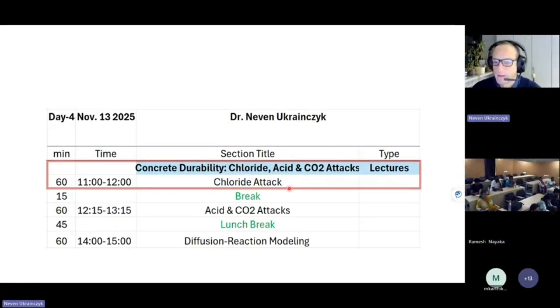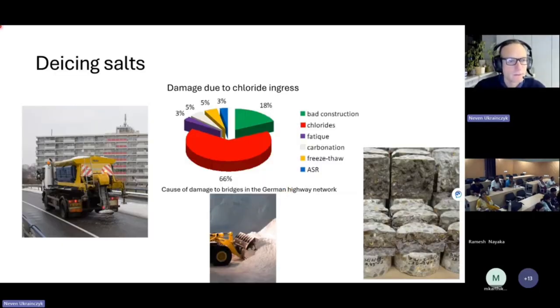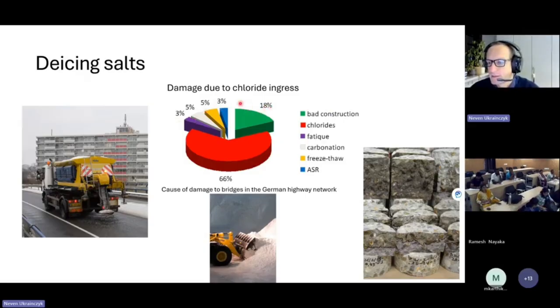This is the most common durability issue. And here you can see this in Germany. It's mostly de-icing salts. But in general, chlorides account for about 66% of the damage to bridges on the German highway network. We can see also here in Germany, bad construction 18%, and then there are other durability issues: carbonation 5%, fatigue, freeze-thaw resistance 5%, and alkali-silica reaction 3%. But the majority is due to chlorides.